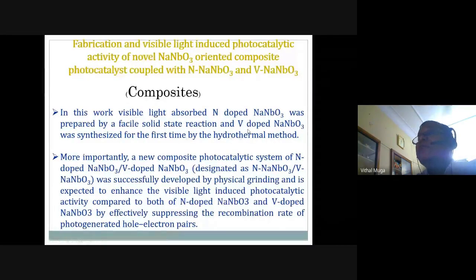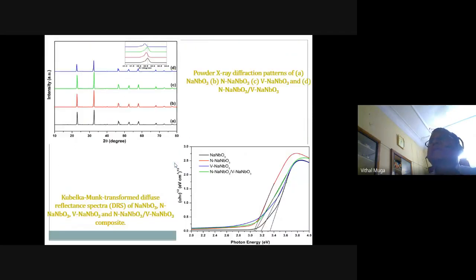Now for V doped, while preparing itself, we take 1 minus x Nb and x of vanadium precursors and use the hydrothermal method for the preparation. Now what we have done is, we have taken these two, N doped and V doped, and then mixed them physically. Physically we mixed and then studied its properties. Now something really interesting has happened.